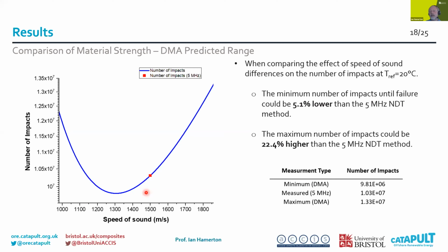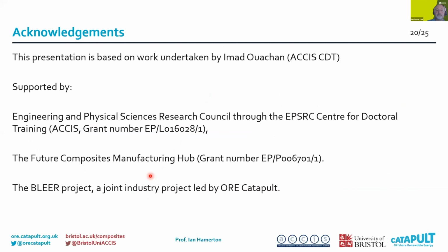Well, it means that if we are able to move beyond this single plot, it indicates that the minimum impacts on a coating before failure could be seriously underestimated. We could be talking about a value that's 5% lower than the NDT method. Conversely, the number of impacts that it could withstand could be significantly higher. So being able to sharpen this model to reflect this gives us a better range of understanding.